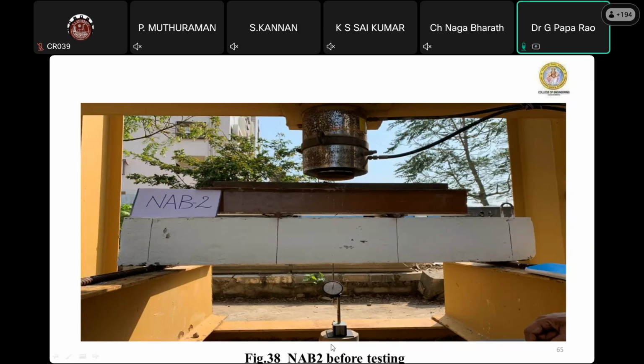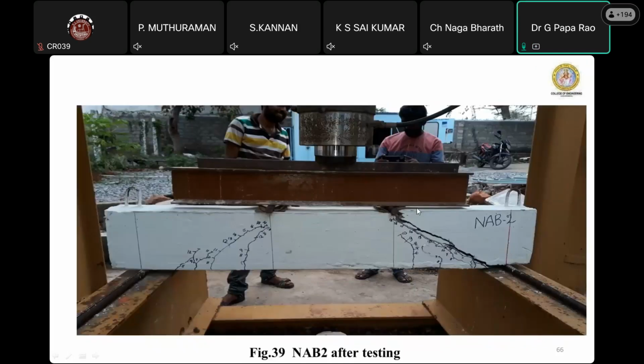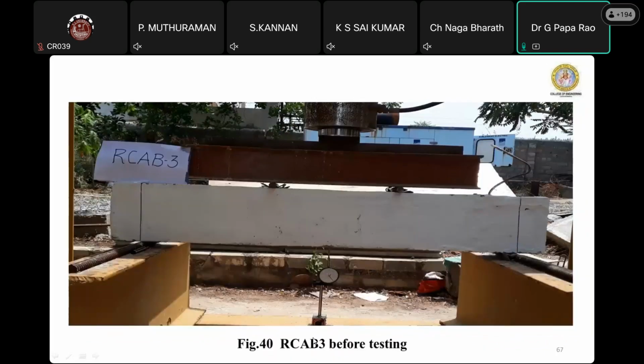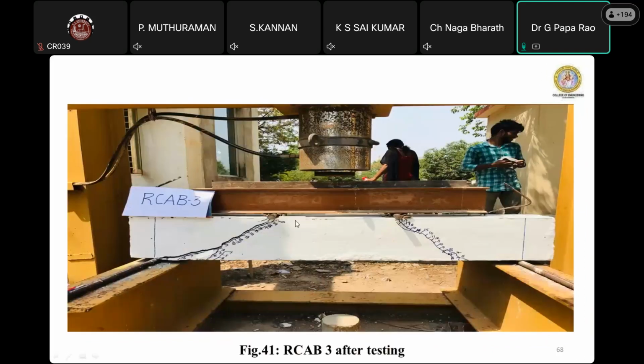NAB2, and this is the NAB2 after testing. So we have allowed this beam to fail in shear. It failed in shear. Similarly, RCAB3, this is 25% recycled coarse aggregate and 75% natural coarse aggregate. This is before testing. You can see it also failed in shear.